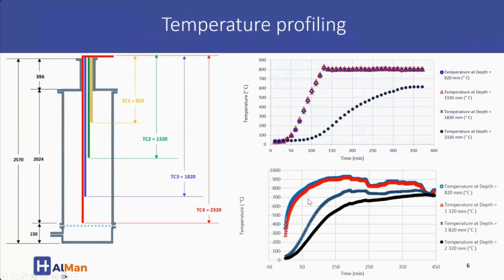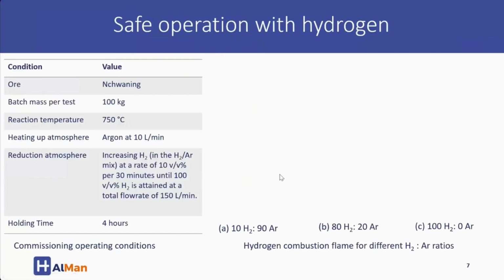That seemed to work, as our target temperature was around 700 to 750 degrees Celsius. After profiling, we were happy to continue with the first hydrogen pre-reduction tests.